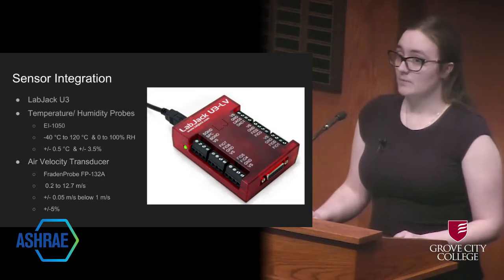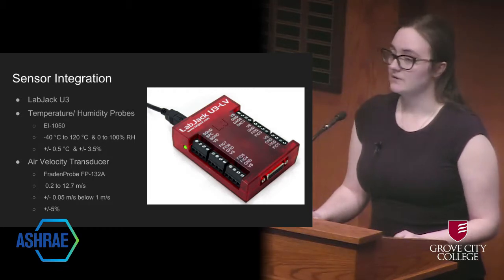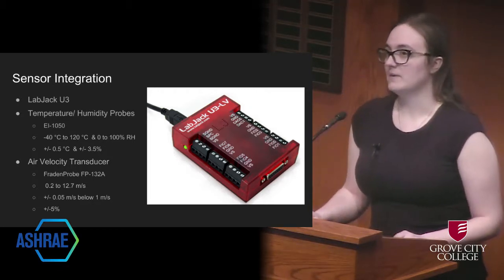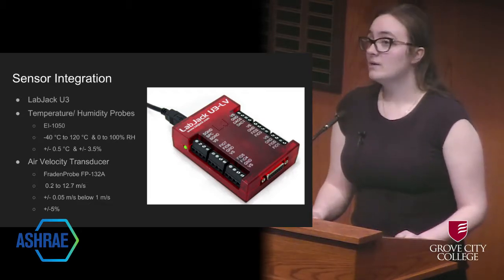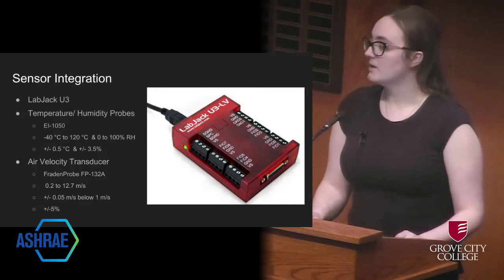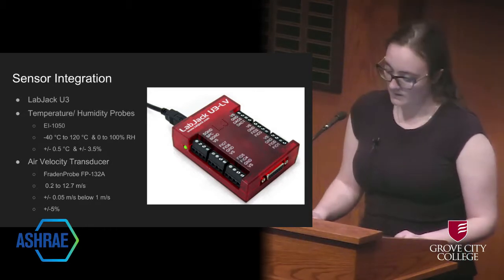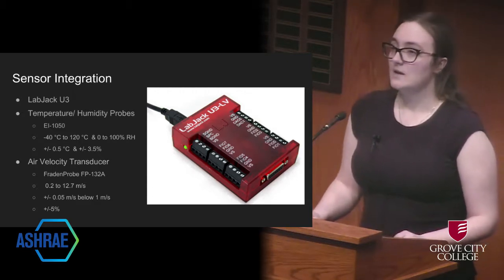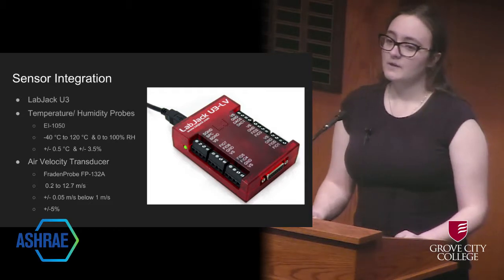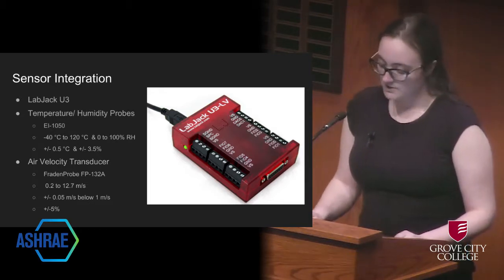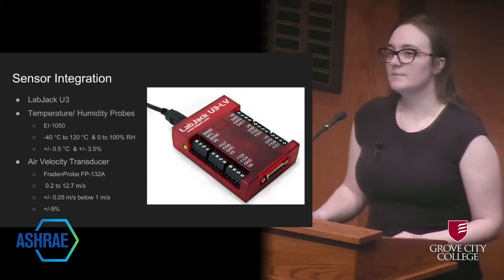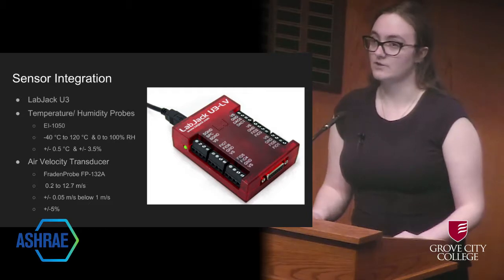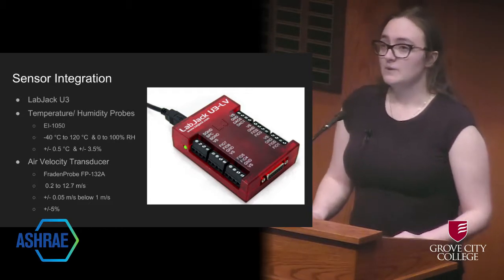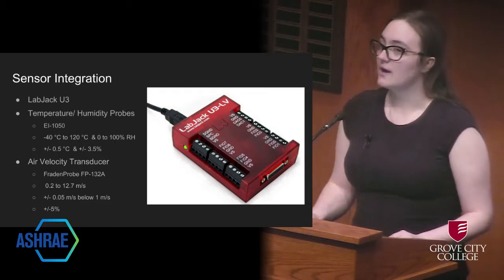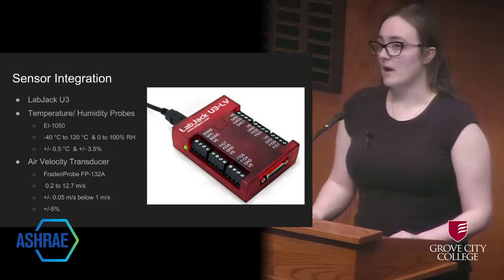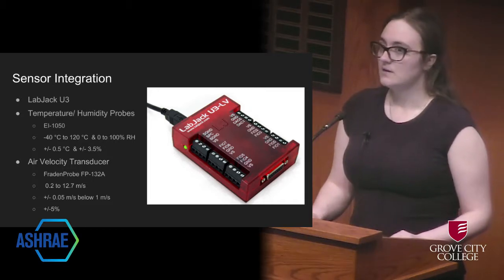The operating range for these probes was between -40 degrees Celsius and 120 degrees Celsius, and from 0 all the way to 100% relative humidity. Now, the accuracy of these probes was 0.5 degrees Celsius and plus or minus 3.5% relative humidity. Now, these probes were specifically useful in our design because they were compatible with the LabJack, meaning that there is a library of functions in order to get these readings. Additionally, they would work well with our system because the temperature and humidities we are reading are well within the operating range. And as for the accuracy, since we want a relative humidity of under 30% in the drying channel, and we expect a relative humidity of around 20%, the plus or minus 3.5% is no big deal.